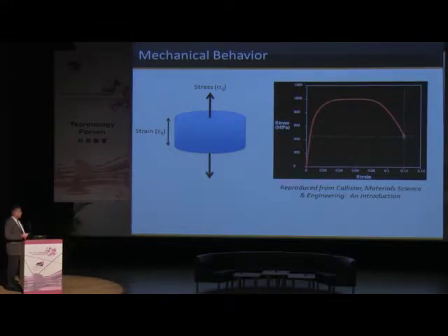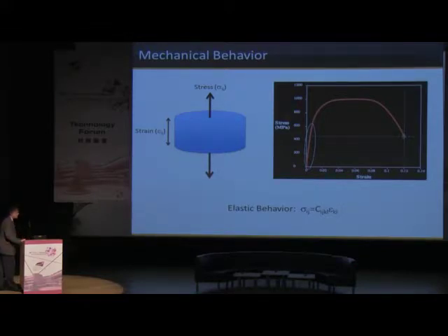Now, there are certain features on this curve which are interesting in terms of engineering a material for mechanical performance. One is the initial slope. Okay, this is the linear slope here, where stress is linearly related to strain. We call that the elastic regime. If we load it and then unload it within this regime, we go back to the original material. Okay, so the relationship between the applied stress and the amount of strain is the elastic constant tensor that I mentioned earlier, the C_ijkl. Okay, there are other features like we go beyond a certain stress level, and then when we release the load, we don't recover back to 0% strain. We start to have plastic deformation. And we call that the strength of the material or its hardness.